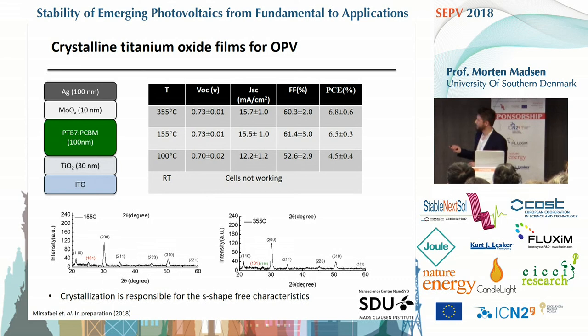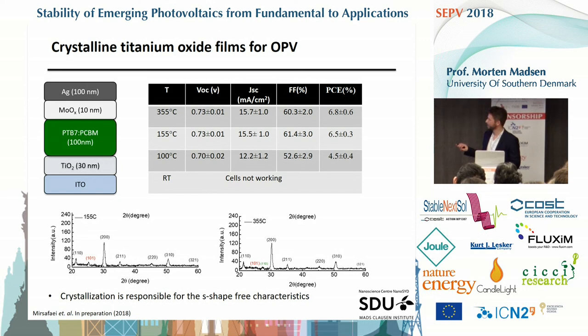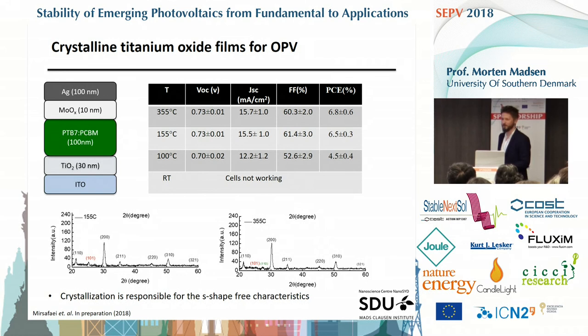At room temperature with amorphous films, devices basically don't work. Going to 100°C, we start to see devices working but with a little bit of S-shape. Going to 155°C where we have the crystalline peak more clear, devices are working well with no S-shape to begin with. We would like to look into stability of these titanium oxide-based cells also, but this is ongoing work.